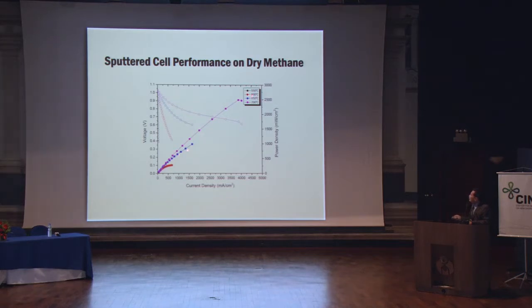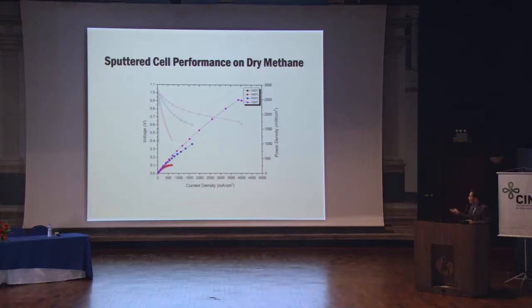Even at 650, we didn't go all the way, but if you extrapolate, it can go up to about 2 watt per square centimeter. And it's been duplicated, and we've operated it, of course still for a short time, only about 10 hours, and we didn't see any carbon deposition or anything like that. But of course, further work needs to be done to prove long-term operation on dry methane.